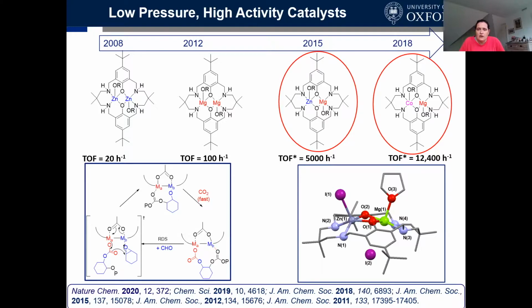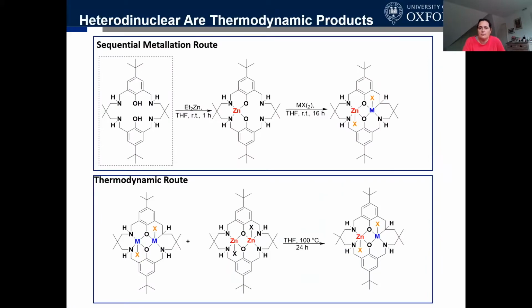One of the reasons we began looking at heterodinuclear catalysts was that this mechanism that we'd studied for homodinuclears was pointing us towards different roles for the two metals. I'm going to leave it at that for now and show you about making cobalt magnesium or zinc magnesium catalysts. The important point here is that it took us a number of years to deduce this, but the heterodinuclear metal complexes are actually the thermodynamically more stable product compared to the homodinuclears in most cases. Of course, this is not always true, but certainly in the cases that I'm going to show you today, it is so. This means we have two different synthetic routes.